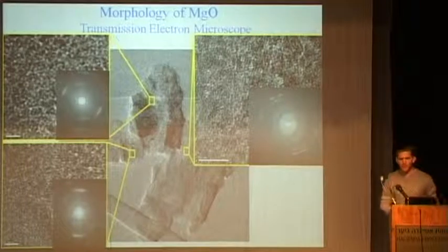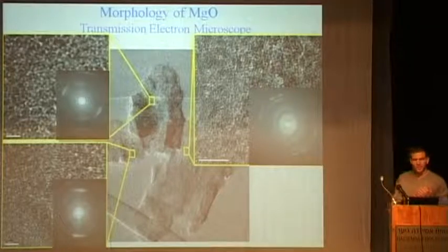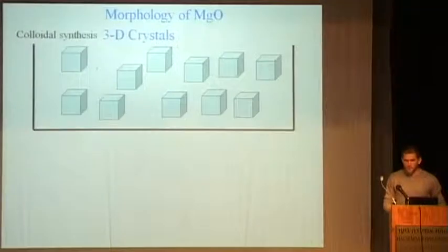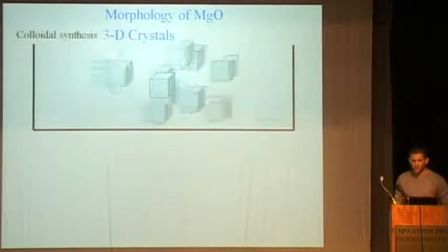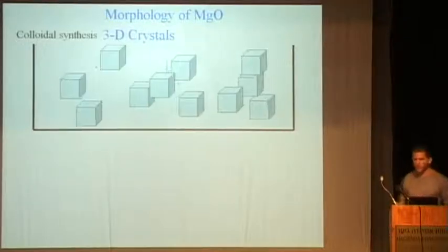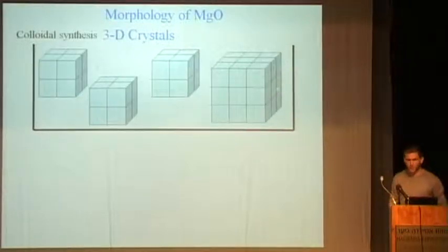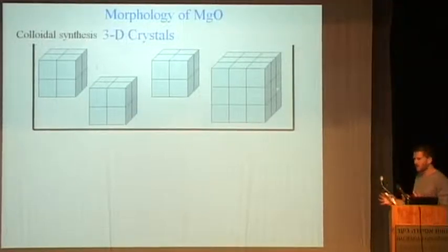You need to understand that it's very, very unique to have a two-dimensional sheet morphology in a colloidal synthesis. Why is that? Because in a synthesis, you have particles that float inside your solvent. They will try to have the minimum energy, which is the minimum surface-to-volume ratio. This is why they will assemble as three-dimensional particles.